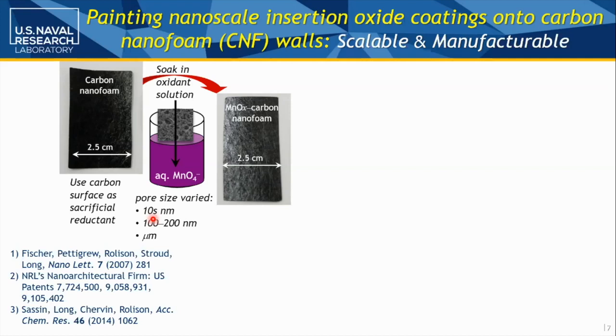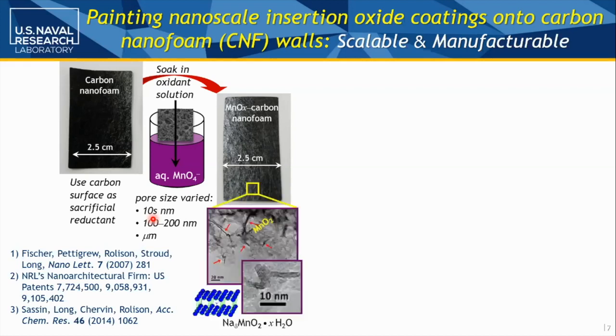So we're going to dip it into an oxidant solution like aqueous permanganate. And if we've controlled what we need to control, and that's usually temperature and pH, what comes out looks as though it's unchanged. But if you go into your transmission electron microscope, you can see the manganese oxide fibrils everywhere. Occasionally you catch them sort of edge on, and you can see the layered MnO6 octahedral planes characteristic of birnessite MnO2. Now, the important thing about doing it this way is most manganese oxides are rocks. They're not great electron conductors.